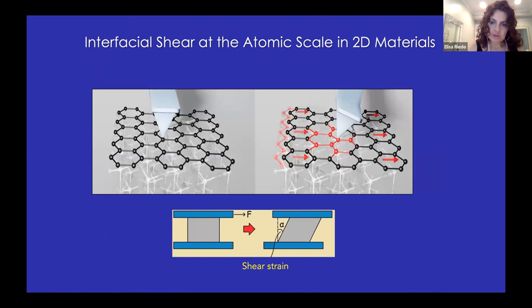So we were interested now not in studying the transverse elasticity in the direction perpendicular to the plane, but in studying the shear elasticity. The way we started to look at the shear elasticity was by using very small loads that give rise to extremely small indentation. When I say small indentation, I'm really talking about sub-angstrom, maybe 0.1, 0.2 angstrom. So essentially almost zero indentation, right?